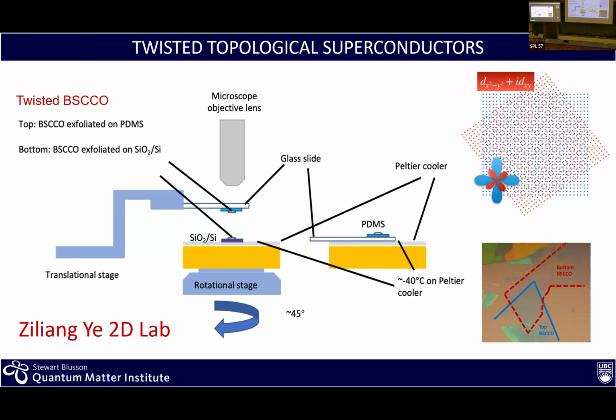Now, the key, though, and this is something that was really developed by Philip Kim, is it's very easy to degrade the surface, to lose oxygen through the surface during this process, and have even reconstruction at the surface. So what was developed was an approach where the samples are being prepared at low temperature so that as you do the stacking and lifting, the sample is cold. In fact, this has been pushed down to about minus 90 or 100 centigrade. And of course, it has to be done in a glove box with very low humidity. Otherwise, you start getting water onto it and it becomes a real problem.